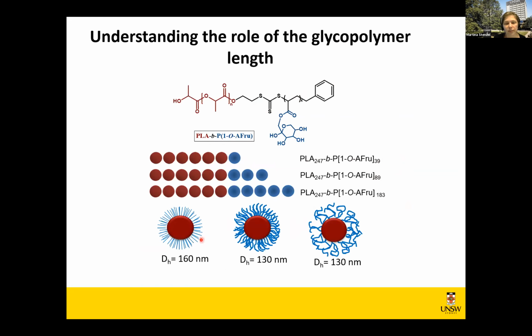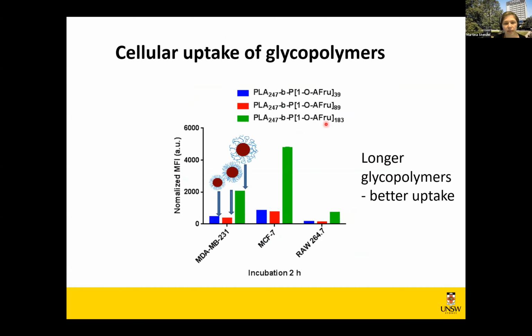They have roughly similar sizes, but the bottom one has a very, very hairy shell. So our polymers are in a very hairy arrangement. And what we find is that we have a much, much better uptake by these longer polymers. And it doesn't matter what cell line we're using, longer polymers are much better in promoting this uptake.